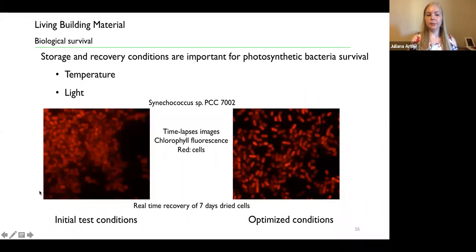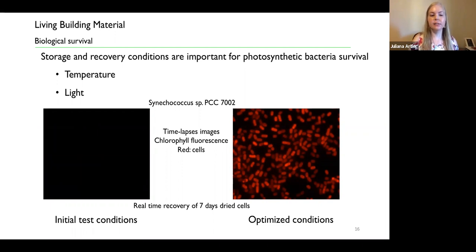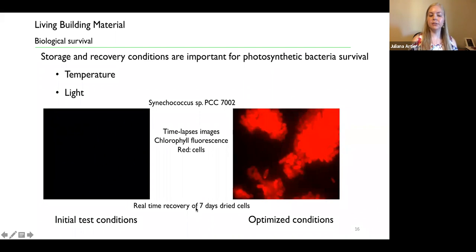So to try to understand a little bit more about how these cells are surviving after desiccated, we also tried different types of parameters that would be important for a photosynthetic organism survival, such as temperature and light during both storage and recovery. And if we see here in this video, in our initial conditions where we didn't optimize the temperature or the light of the recovery, you can see that the cells here completely lose their chlorophyll fluorescence, showing that they are inactive and possibly dead. But once we optimize the conditions for recovery and storage, we were able to highly increase the survival of the cells. As you can see here, they are happily dividing under these optimized conditions, even after being completely dried after 7 days.